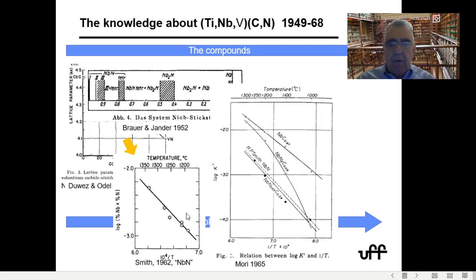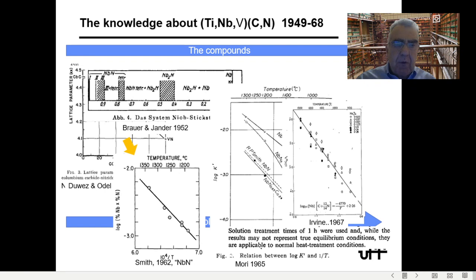But 3 years after that, Mori in Japan tried to measure now the carbide solubility, and he also observed the non-stoichiometry of the carbide, and he noticed, of course, a different solubility product compared to Smith's value for the nitride. And he also noticed that the composition was not just niobium carbide or niobium nitride, but there was miscibility between the phases or between the compounds. Then Irvine tried to handle this by introducing an atom-to-atom ratio here, but this is not really a good solution because you're not really taking into account the mixability of the two compounds.